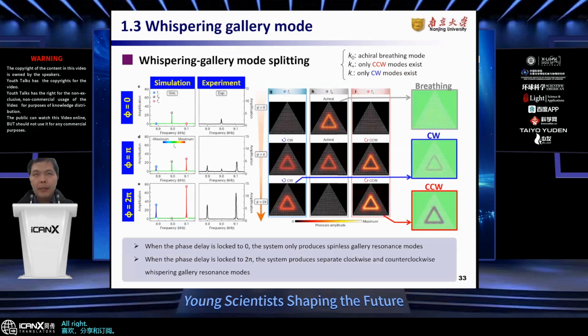All right, let's dive into this theory a bit deeper. To test it, we did some numerical calculations on the amplification factor, considering different gain phase textures. Amplification is how much louder the sound is along the whispering gallery compared to along the straight domain wall. Looking at this rainbow colored map, it shows the sound intensity along the domain wall for waves going right or left. The counterclockwise and clockwise modes